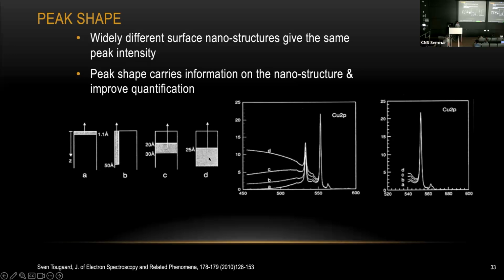When you go ahead and do the high resolution scanning for the copper signal, the intensity and everything looks pretty much the same. You can't differentiate anything at all. But looking at the background, you actually can find out which region of the sample you are detecting the signal from. From sample A, right from the top surface, there's very, very low background signal. But if you pick out your signal much deeper, now you can see there's a lot of background. So when you're looking at your XPS spectrum, if you see a huge background signal next to your main peak, it means your signal is actually coming from somewhere much deeper inside your sample. Or maybe there's some layer of contamination on the surface, and that can also generate this high background signal.